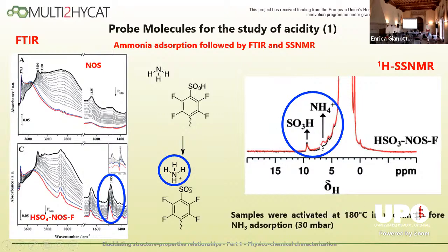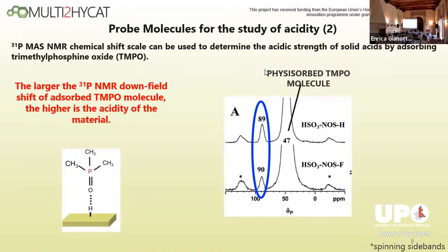So we did the same experiment, treated the sample, sent ammonia, and we can monitor the increase of the ammonium ion signal in the proton NMR and a very slight decrease in the sulfonic group proton signal in the spectrum after ammonia adsorption. This gives us an indication of the presence and availability of these acid groups. But if we want to have an idea of the strength of the different acid groups, we can move to the use of trimethylphosphine oxide as a probe molecule, which allows us to place our materials on a scale of acidity, because when trimethylphosphine oxide is adsorbing on acid sites, we can follow the signal in the solid-state phosphorus spectrum, and the larger is the downfield shift of the signal, the higher is the acidity of the material.